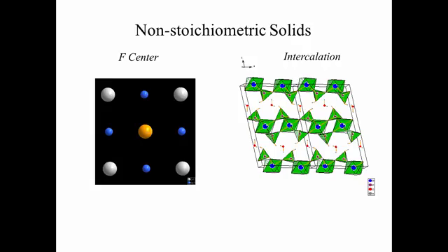For example, here we have something different where there's supposed to be a chloride, and maybe we've heated up the structure and it's lost chlorine and left the electron in this hole, and this is called an F-center defect because from the German Farbe, which is the word for color. So sodium chloride is a colorless compound. When you excite the compound, maybe heating it, or we can excite it with X-rays, and it will lose chlorine, leave these electrons. Now these electrons are free to move around and will actually give color to the compound.